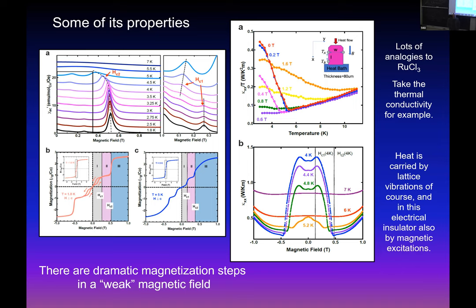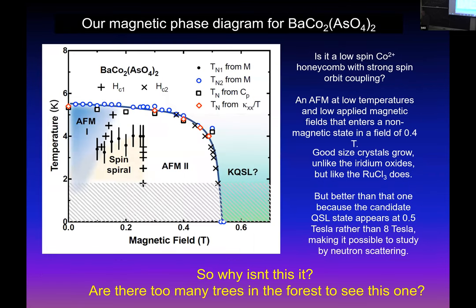So basically, you have the arsenic oxygen tetrahedron on the barium, which puts the cobalt just the right spacing apart so that you get what looks like low spin cobalt 2+, and you get the same thing that you get in ruthenium trichloride, but you get it at 0.5 tesla, which is accessible in a neutron scattering experiment. Have you ever done a neutron scattering experiment? It's hard to get a field that big on something as big as you need to do a neutron diffraction experiment. Neutron diffraction is very sensitive to magnetic excitations, but you have to put the sample in a field of less than 2 tesla, 1.5 tesla, something like that. So the problem with ruthenium trichloride is you need a field that's much, much bigger than that.